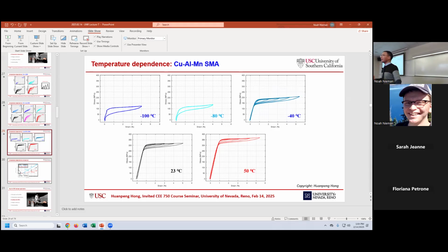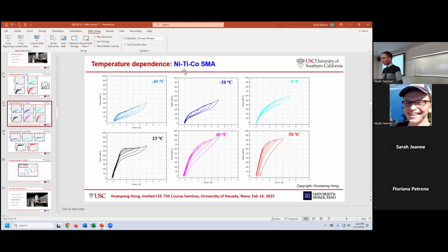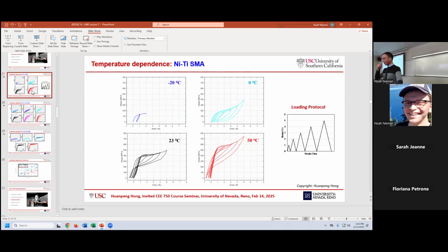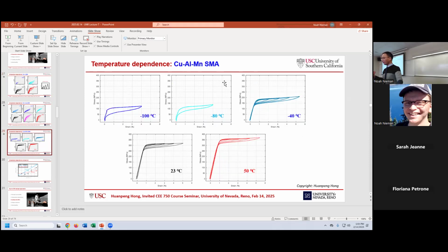We indeed did some DSC tests to measure the austenite finish temperature. For the nickel titanium ones, the austenite finish temperature is 0 Celsius. And for the copper aluminum manganese alloy, the AF is, I think, -40 Celsius. So then you're not comparing apples to apples. You already have a material that works better in cold, and now you're saying the other material is not working in cold. So you need to keep the AF of all of these alloys the same, then you can play with the temperature range.